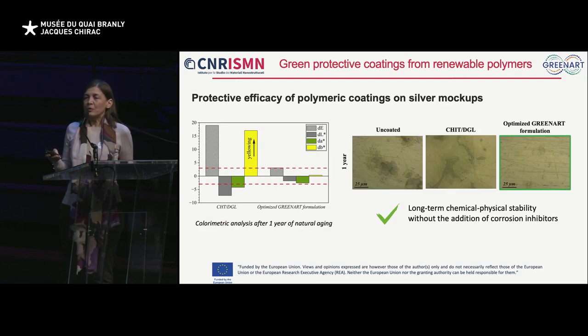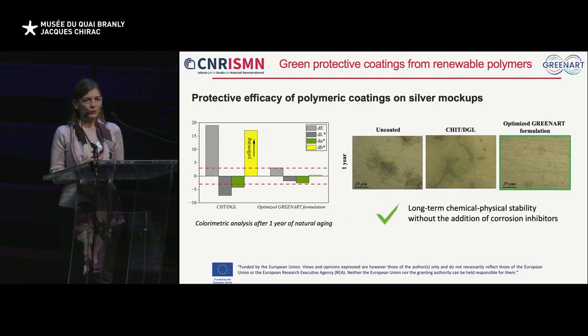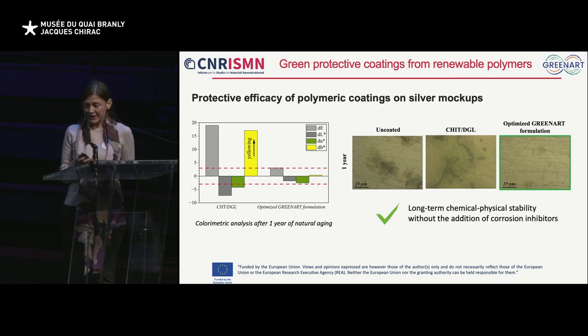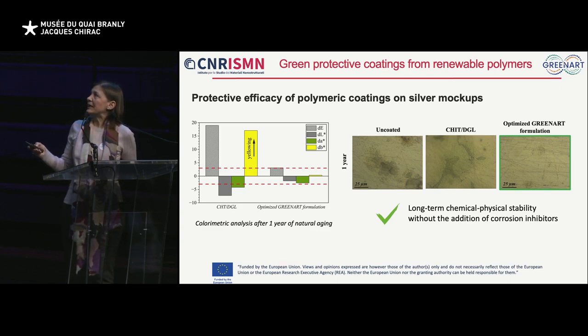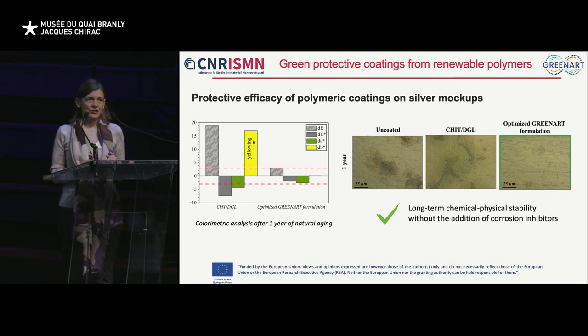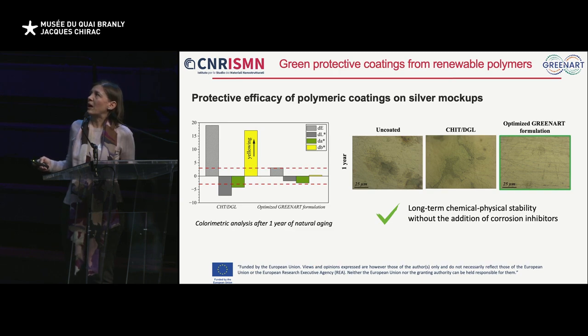So the next step was to test this new formulation also on silver. And in this case I just showed the results of the natural aging treatment, and after 1 year we can see that by comparing the uncoated substrate, the substrate coated with the previous formulation and with the new one, we have an improvement of the protective efficacy.